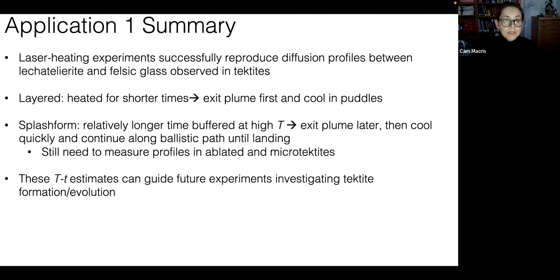So to summarize this first study, laser heating experiments successfully reproduced diffusion profiles between lechatelierite and felsic glass observed in tektites. The layered tektites were heated for shorter times. We think they exited the plume first and cooled in puddles. The splash form tektites were buffered at high temperatures for relatively longer periods of time. They exited the plume later, then cooled quickly, continuing along their ballistic paths until landing. We still need to measure profiles in ablated tektites and microtektites to more fully understand the impact plume. But the temperature-time estimates we have so far can guide future experiments that investigate tektite formation and evolution.